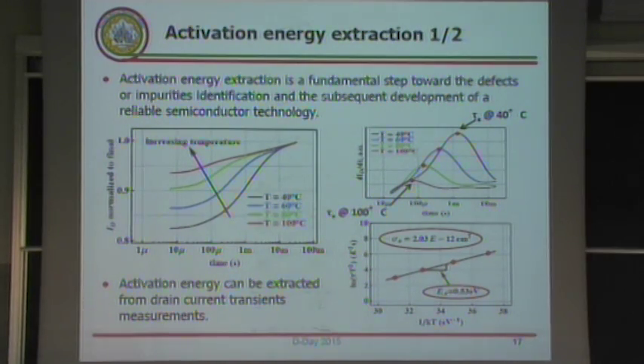So how do we measure the activation energy? We perform again drain current transient, but this time we measure the drain current transient at different temperatures, as you can see here, and then by deriving the current curves, we obtain the value of the emission time constant at different temperatures. For example, at 40 degrees, at 60, and so on. And here you can see the emission time constant at 100 degrees.